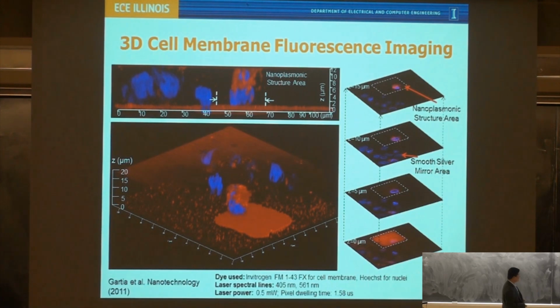Now what we also do, because in confocal we can do z-axis sectioning, is take two-dimensional images at 0 micron from the surface, which means on the surface, and 2 microns, 5 microns, sorry, 5 microns from the surface, 10 microns, and 15 microns. You see that we can see the fluorescence enhancement very clearly, not only on the surface, but also well above the surface. This is well beyond the so-called near field enhancement distance.